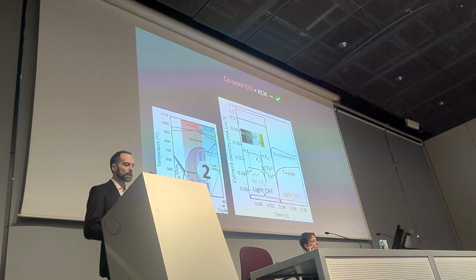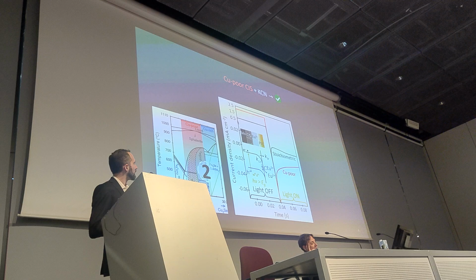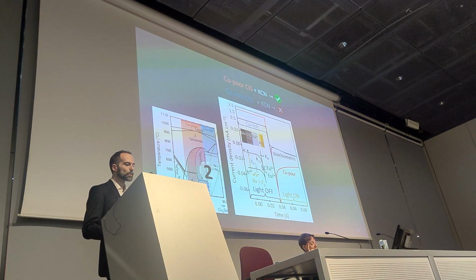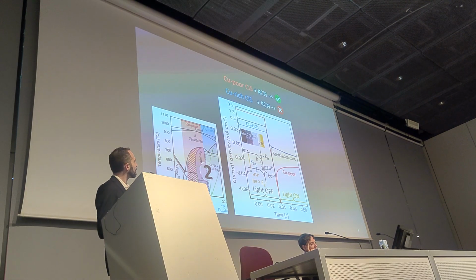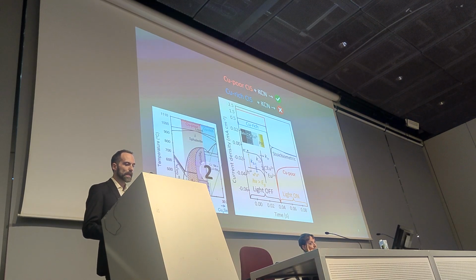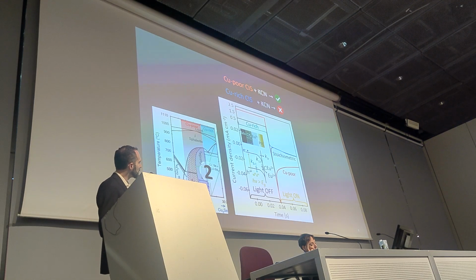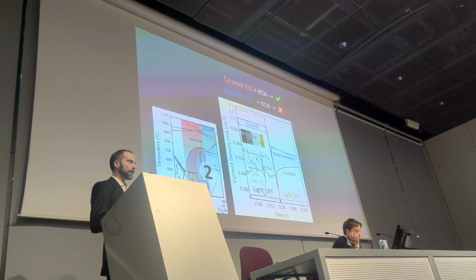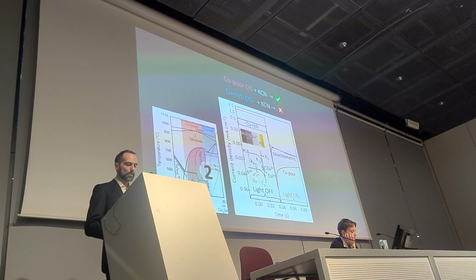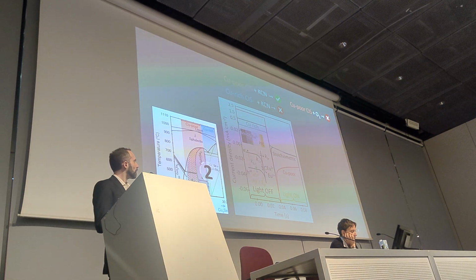As we move the material composition towards stoichiometry, we can start to observe a change in the transient quite remarkably. As we go to the copper rich, of course after removing the secondary phase copper selenide, we get a completely different sort of transient. There is no way we can understand this sort of transient unless we assume that we have generated a bulk trap. So a defect, we have generated a new defect at room temperature that is not at the surface but slightly beneath the surface. So what is the origin of this bulk trap?